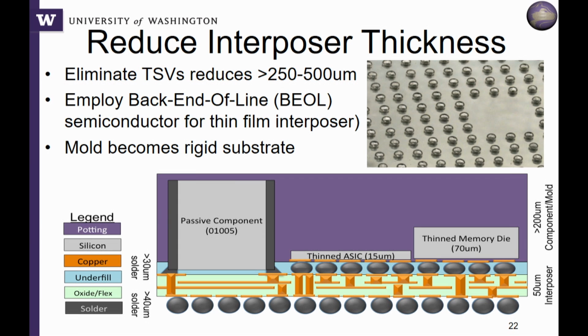In this case, you lose the rigidity of that system, so you have to count on this traditional epoxy overlay to become the rigid substrate. It's quite a challenge to get an epoxy that has a different coefficient of thermal expansion from silicon to match, and not compress and cause contortion.